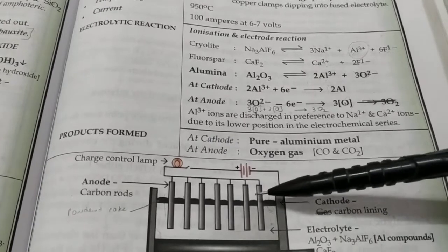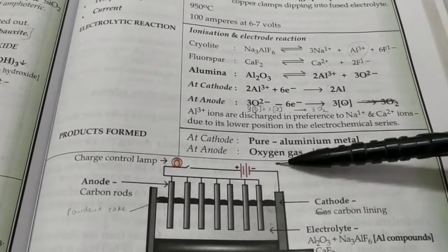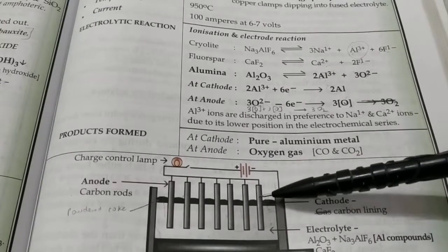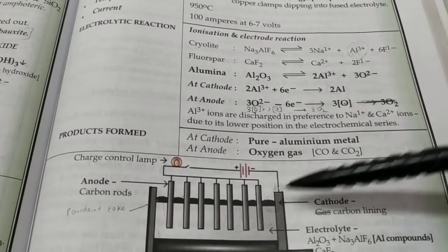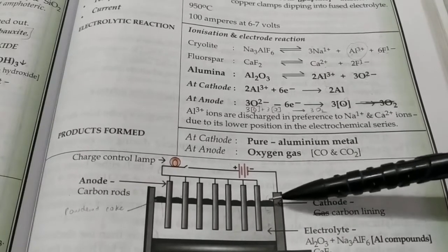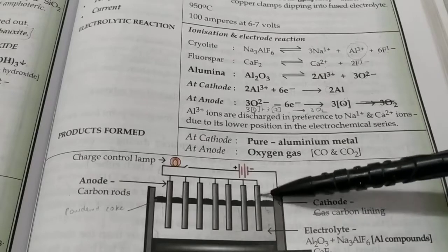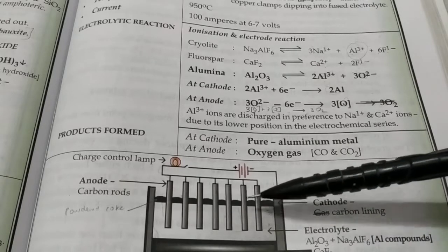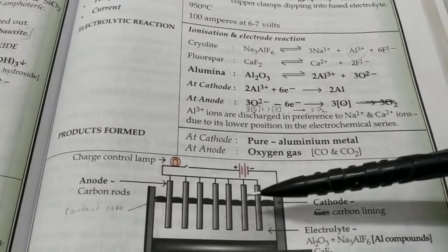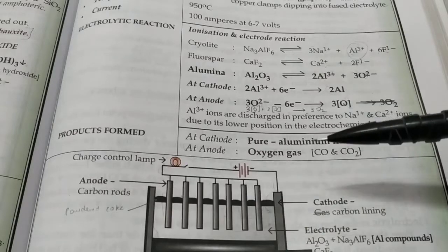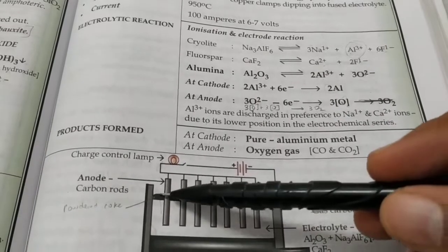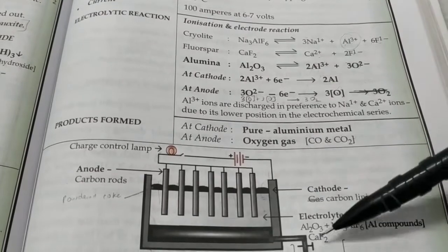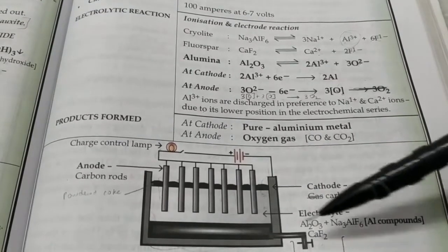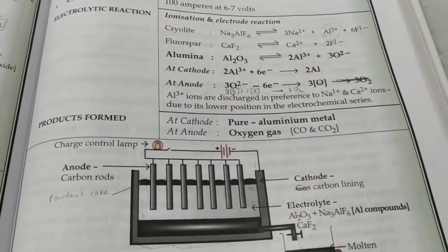By the way, the observation at the anode is not oxygen gas. In fact, oxygen will react with these carbon rods to form carbon monoxide and carbon dioxide. So you will see the anode is getting corroded with time, it diminishes in size, and that is why these anodes have to be replaced frequently. So now a few questions. Why is there a powdered coke on top? And why do we have these additional compounds in the electrolyte? These are all very important give reasons.